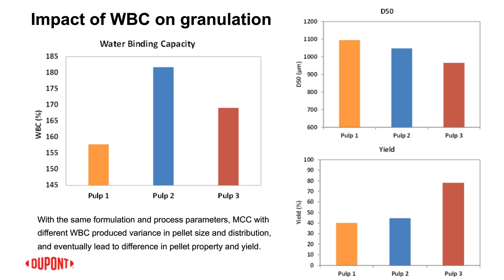They are produced from different pulp, and so they have different water binding capacity, right, as you see on the graph on the left. And we compare them in a theophylline model formulation and use the extrusion spheronization process to make spherical pellets. So they all use the same formulation and went through the same process condition. But they end up with different D50 and also different particle size distribution, which eventually lead to different yield, as you see from the bottom graph on the right. So they give you very different yield.